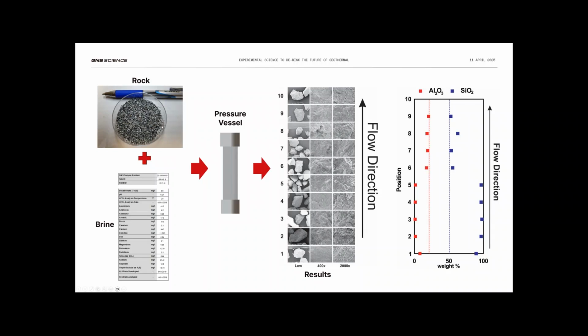So during a reinjection simulation, we take rock. So we actually take rock from the actual location. We ask whoever the client is to provide us with a representative rock from where they think the reinjection horizons are. And we crush it and we sieve it to a certain size fraction and we clean it to get rid of fine material, which reacts differently. We also, as best we can, get a brine from the actual location if it's available. If a brine is not available, we can reproduce the brine as best we can from chemistry analyses.